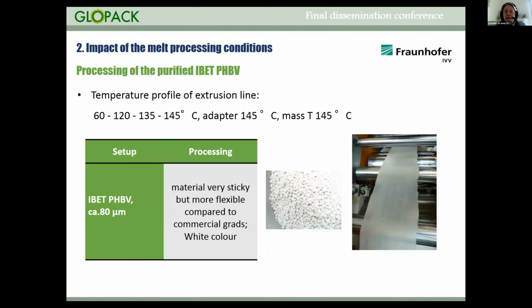And on the next slide, here you can see the results we received with the GLOPACK material produced by IBET. If you compare the used temperature profile, you can see lower temperatures were used in comparison to the commercial grade due to the higher HV content. And you can see also on the picture that the color of the project material is white, or the film looks a little bit opaque. And the material is again very sticky, but more flexible compared to the commercial grade.